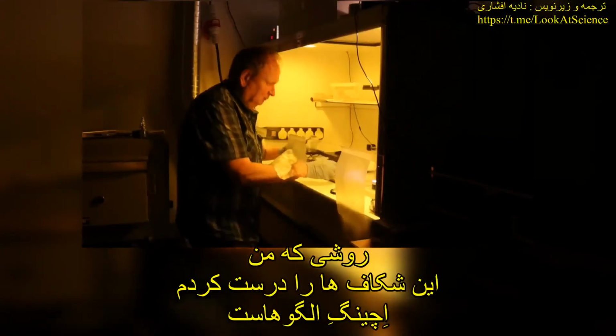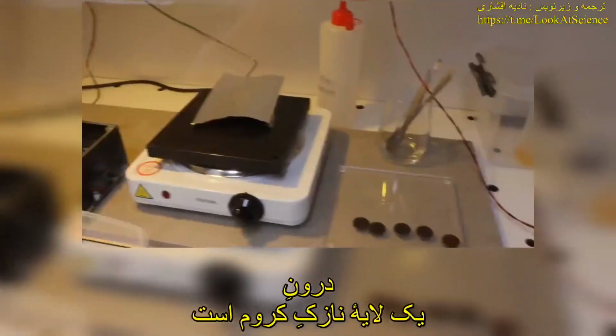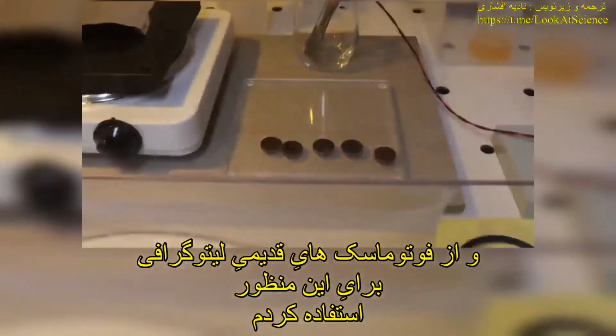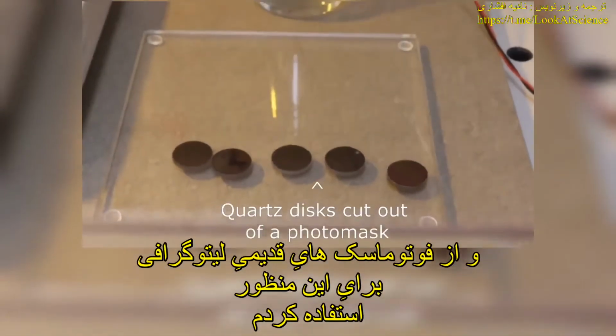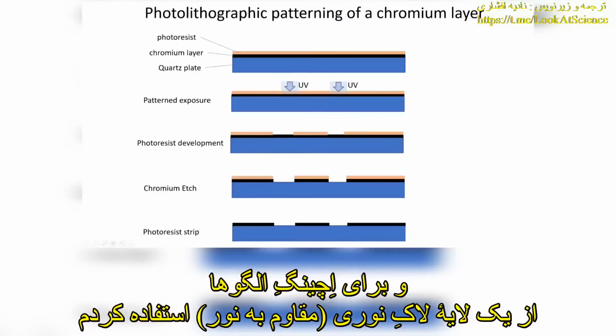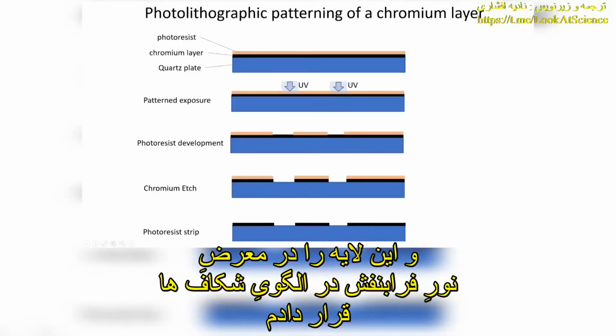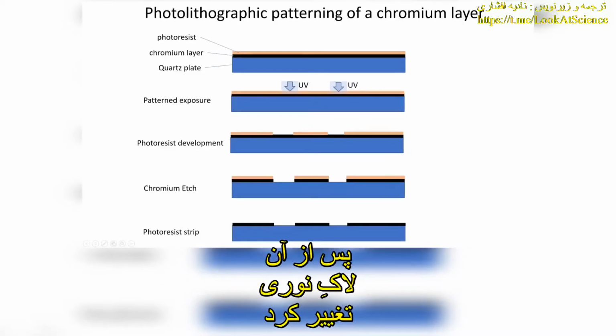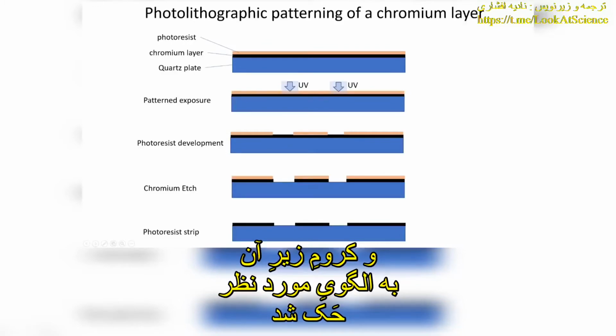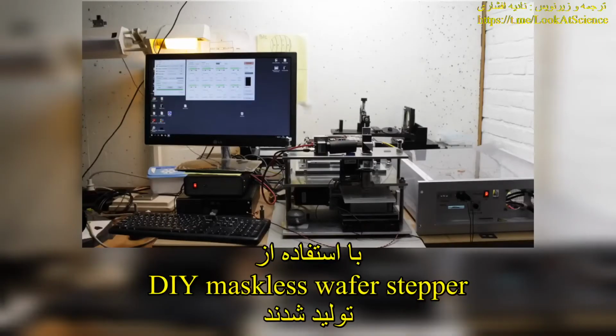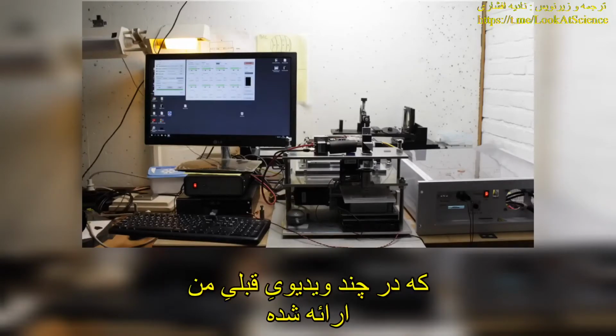The way I made these slits is by etching the patterns into a thin chromium layer, and I used old lithographic photomasks for this purpose. Now, to etch the patterns I used a photoresist layer and exposed this layer with UV light in the pattern of the slits. After that, the photoresist was developed and the chromium underneath was etched in the desired pattern. Now, the result is tiny transparent slits in the chromium layer. By the way, the exposure patterns in the photoresist were produced by using the do-it-yourself maskless wafer stepper that featured in several of my previous videos.